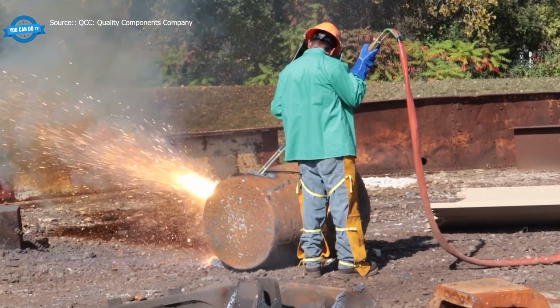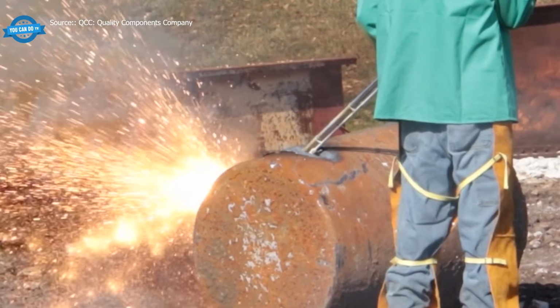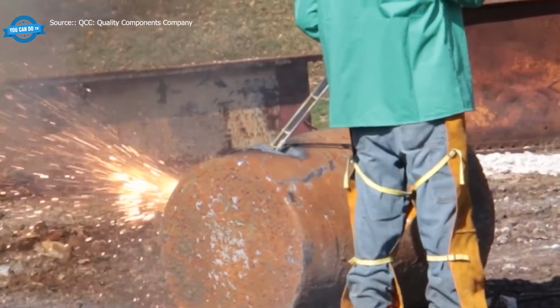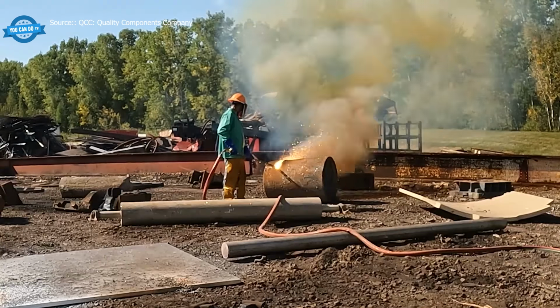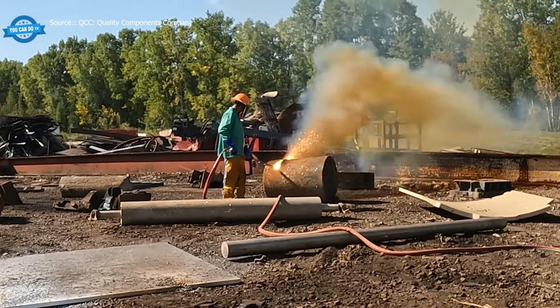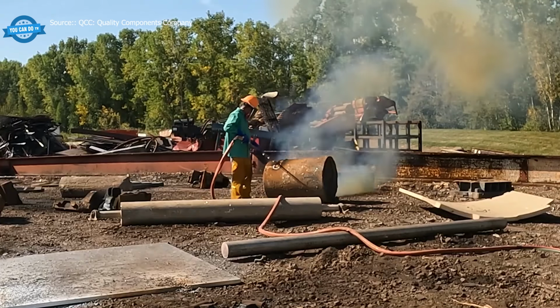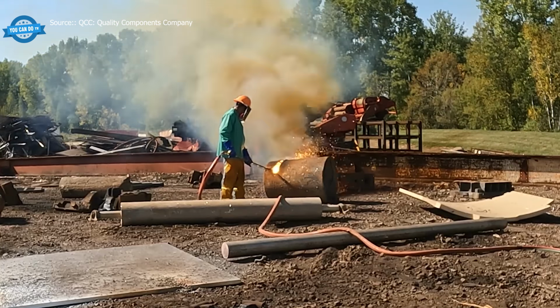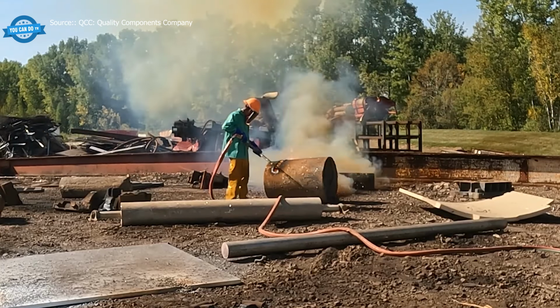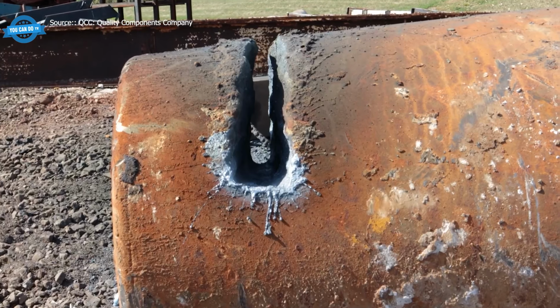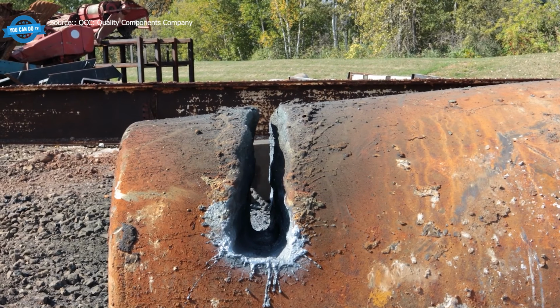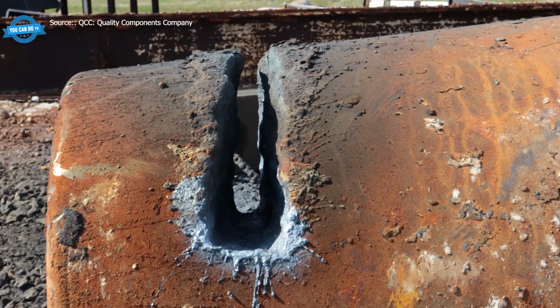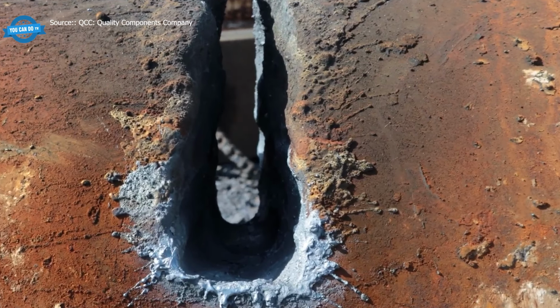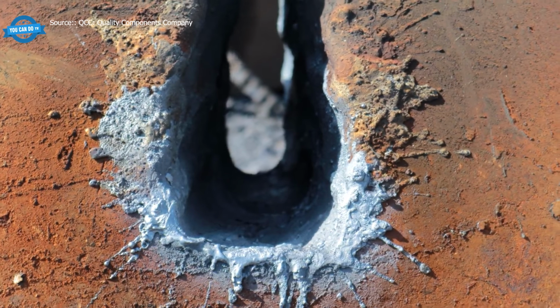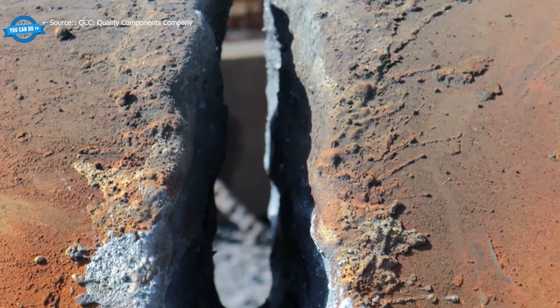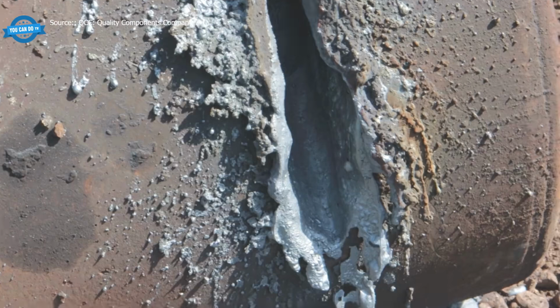Some scrap does not fit through the shredder because some scrap is a 14-ton steel ingot, massive castings that failed final inspection, oversized mill rejects, or heavy industrial pieces that arrived intact at the scrapyard have to be reduced before they can be recycled. A powder-cutting torch handles what an oxy-fuel flame alone cannot. The torch injects iron powder into the cutting stream, and the powder ignites in the oxygen jet at temperatures beyond what a standard flame produces. The result is a cut through solid steel. Sparks the size of tennis balls launch sideways. The ingot splits into manageable sections that can now go into the shredder.